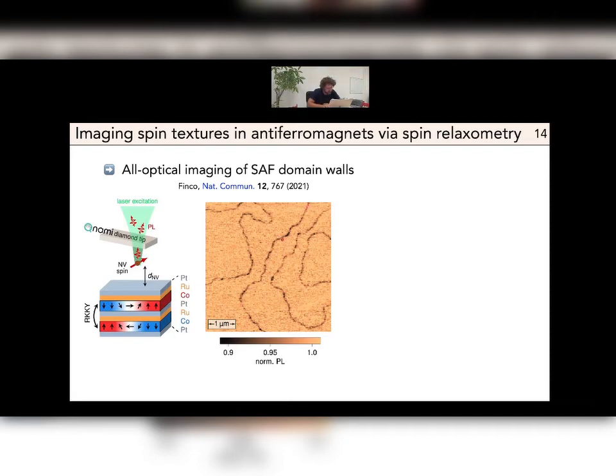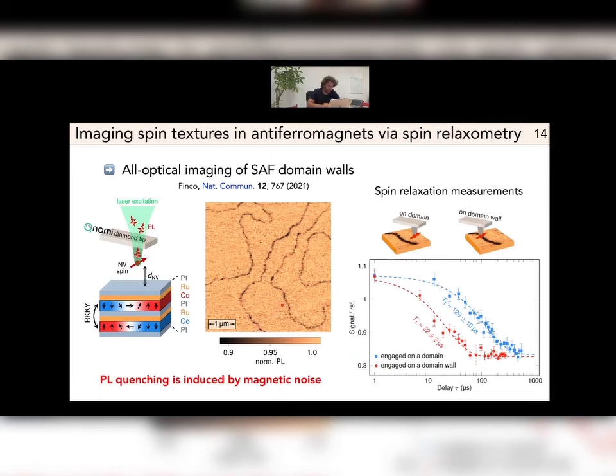To verify here that the quenching is indeed induced by magnetic noise, we did measurements of the longitudinal spin relaxation in two conditions. First, by engaging the tip above the domain and then above the domain wall. And these are the results here. In blue, you can see the measurement when the NV is engaged on the domain. You have a T1 of about 120 microseconds. While moving to the domain wall, there is a sudden drop of the relaxation time, and T1 is brought to 20 microseconds. So here we are sure that this quenching that we see is indeed induced by magnetic noise, and this is supported by this spin relaxation measurement.